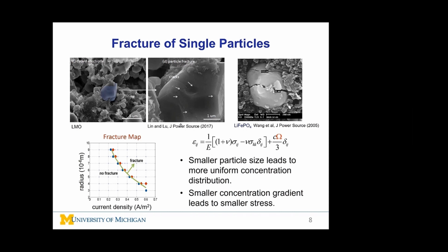With increasing demand for specific energy and energy density, more lithium is integrated into the high energy electrode material. This causes increasing volume expansion of the electrode after lithium integration. The associated stress can lead to various failures in the electrode, such as fracture in the active material particles.